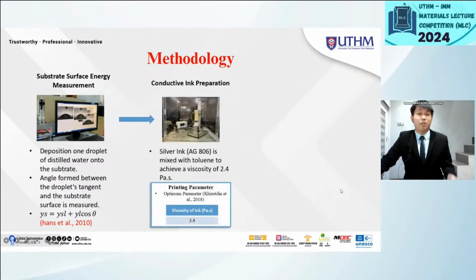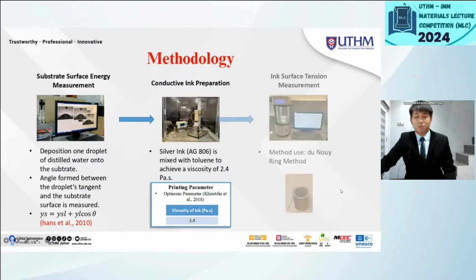The next step involves preparing the conductive ink. For this research, the silver ink used is AG806. These silver inks will be mixed with toluene to achieve a viscosity of 2.4 Pa·s. Once the desired viscosity is reached, the ink surface tensions will be measured using the du Noüy ring method.